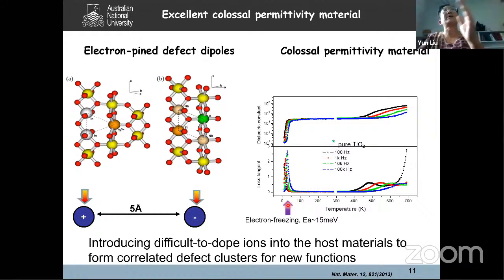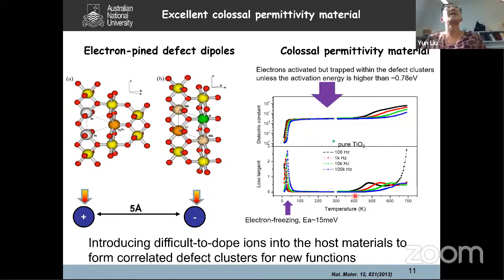Okay, because the electron is light in weight, they can move very fast. So in the measured frequency range, we see no frequency dependence and no temperature dependence, until they have enough energy to excite these trapped electrons out of the trap. Outside, the electrons become free electrons, behaving like a metal, so both the dielectric constant and the loss go up. So you can find this by introducing the difficult-to-dope ions using another extrinsic ion, creating the environment to take this indium in. In that case, we can form the bonded correlated defect cluster to significantly change the property.